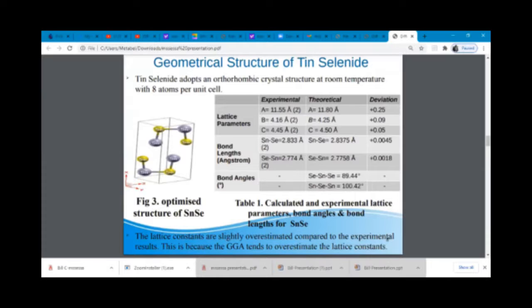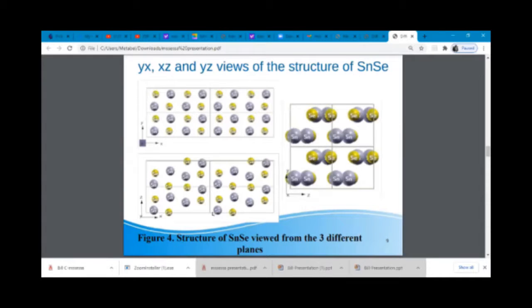There seems to be some small positive deviation. This is expected due to the generalized gradient approximation that was used, which tends to overestimate the lattice constant. And then on this slide, figure 4, this one shows just the same structure, but from different crystallographic planes, the YX, ZX, and YZ planes, and how the electrons are distributed along those planes.